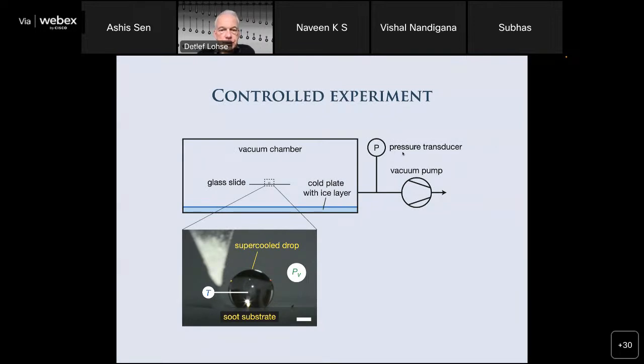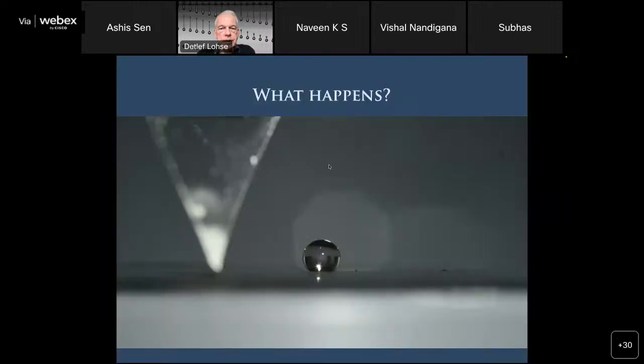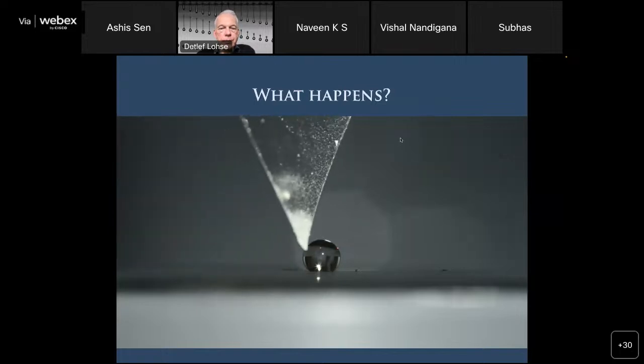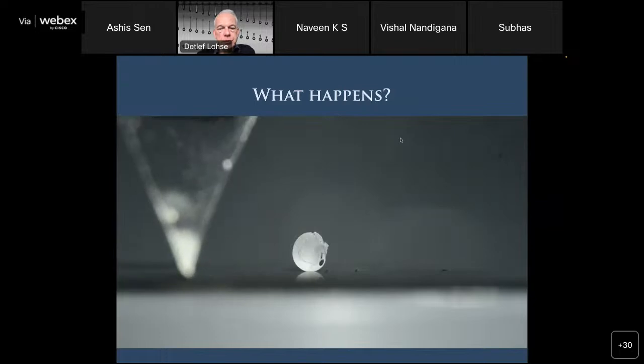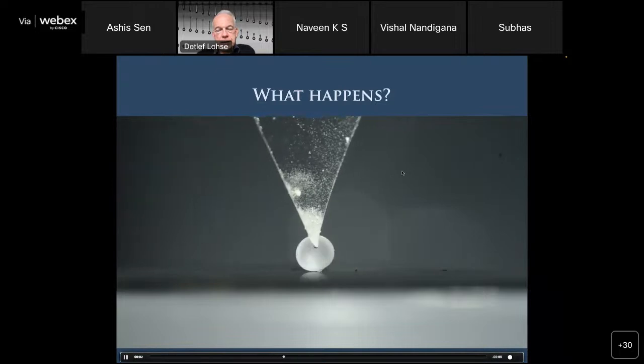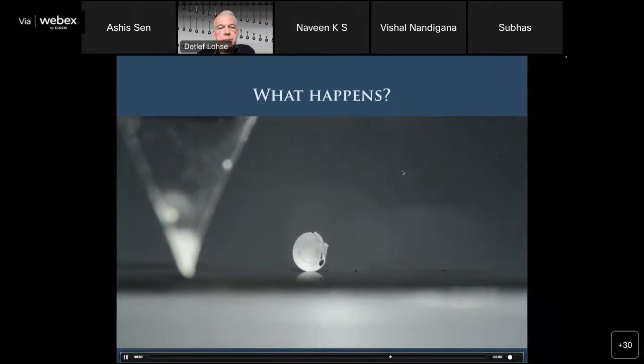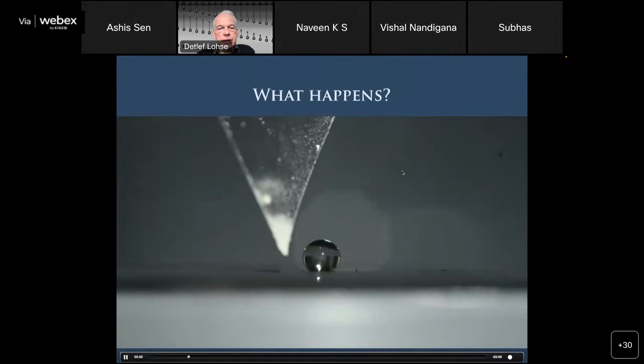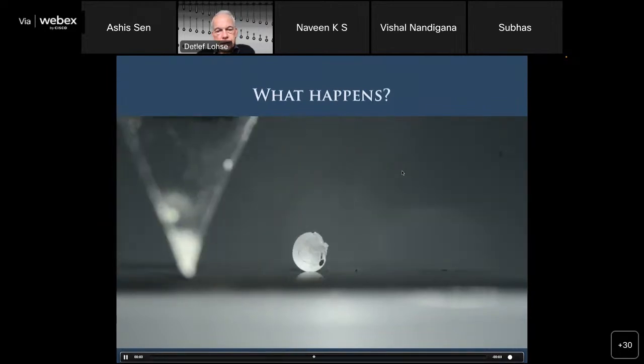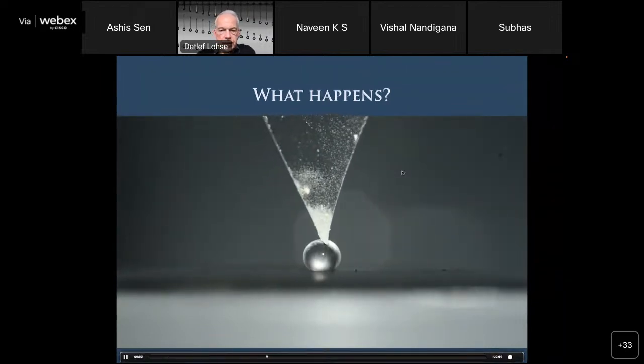What we do is that we create a hydrophobic surface. We put a droplet on top of this hydrophobic surface, and then we reduce the pressure. What then happens is that the water evaporates, and while evaporating, it cools down. So it's supercooled. When you then initiate the freezing, the crystallization of the ice, by touching with some silver iodide, it freezes from outside in, and at some point it explodes. So it's really very, very fascinating.